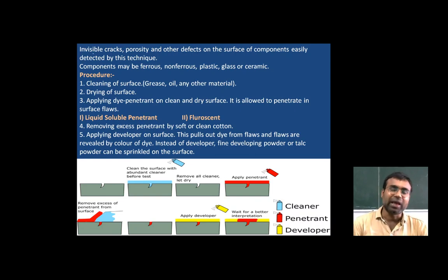Why? If we use a chipping hammer or peening methods, or shot blasting to remove the scaling on the surface which is to be tested by liquid penetrant, the impact of these tiny particles will close the voids which are open on the surface, by directly impacting that location.